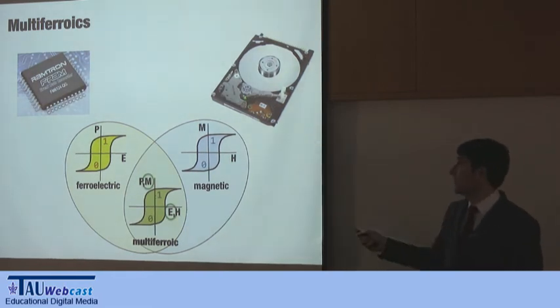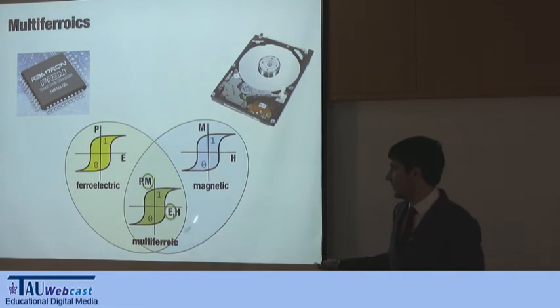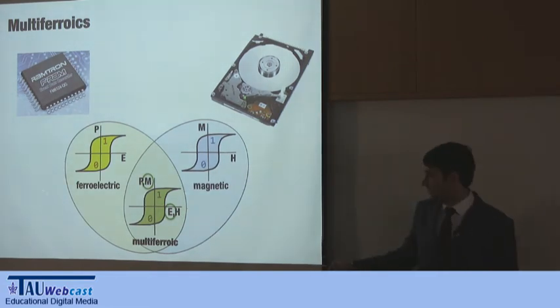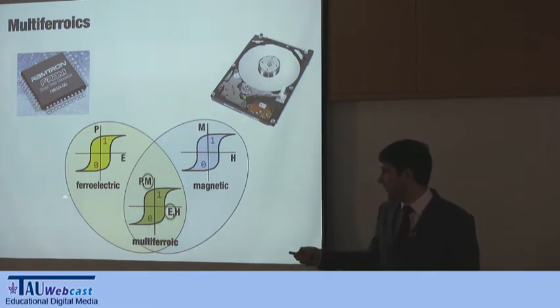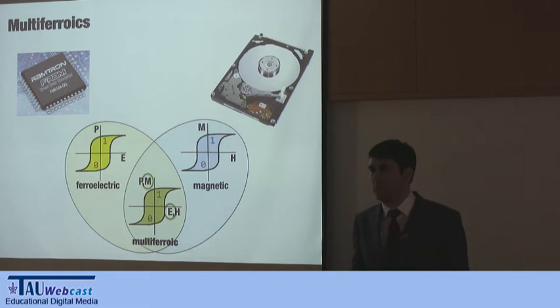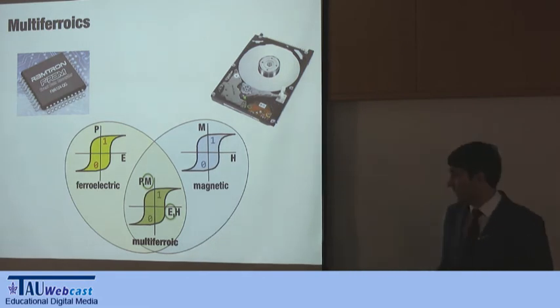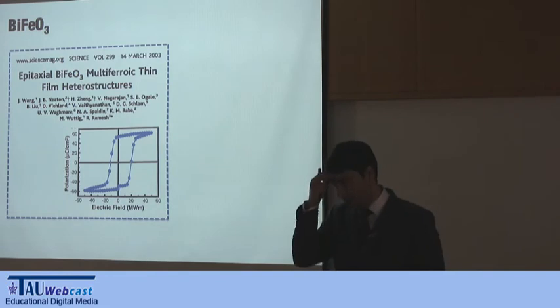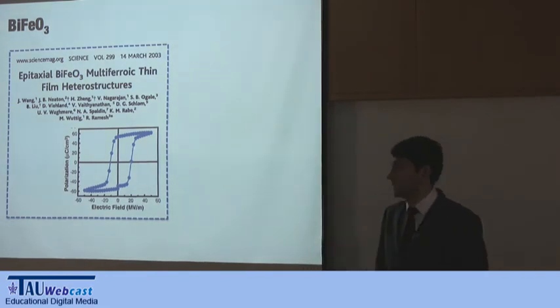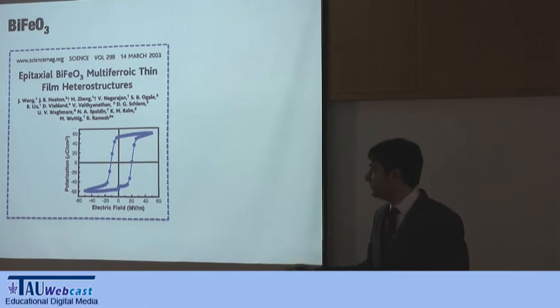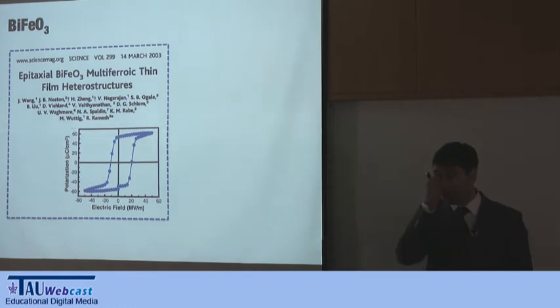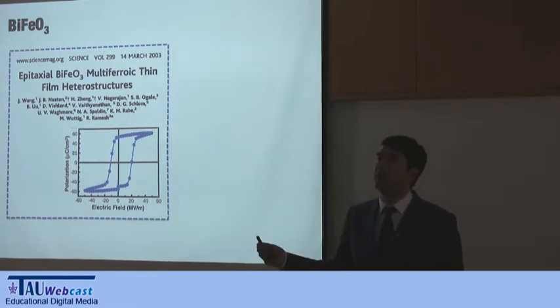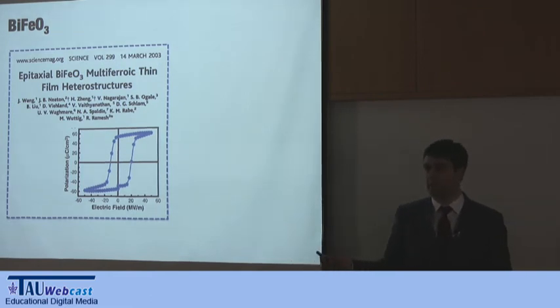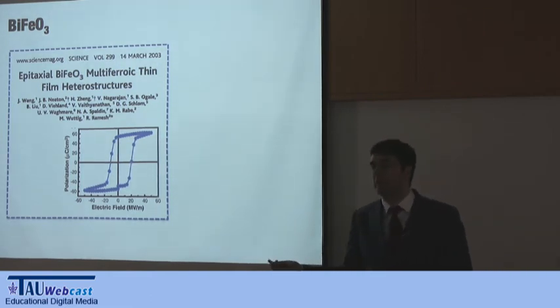And this can be useful because there are problems with both types that maybe are absent with a multiferroic. So a multiferroic is just a material that is ferroelectric and ferromagnetic, although now people also call some antiferromagnets multiferroic. So there's a lot of interest in multiferroic materials, and a lot of research has been done, starting with this paper in which they found that in films you get a polarization for this material that is larger than any of the typical polarizations in perovskites, like 3 times more than in barium titanate, and that they had some kind of magnetic moment.